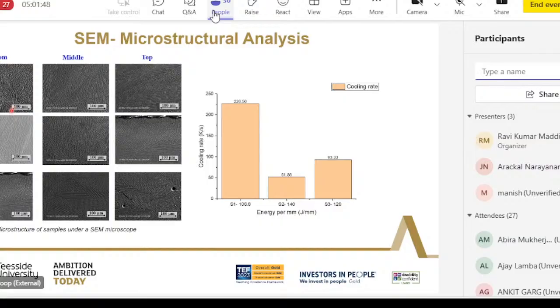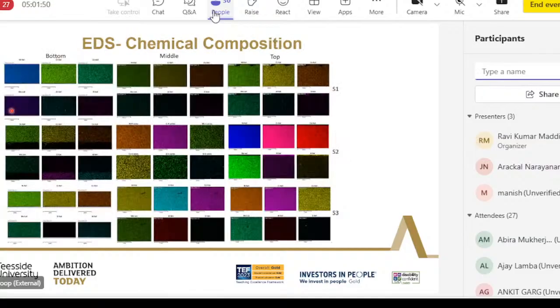And then we did EDS mapping, which again, because of the lower energy density and the lower scanning speed that we were using in this project, we were getting a finer, or uniform, chemical composition for these particular parts.